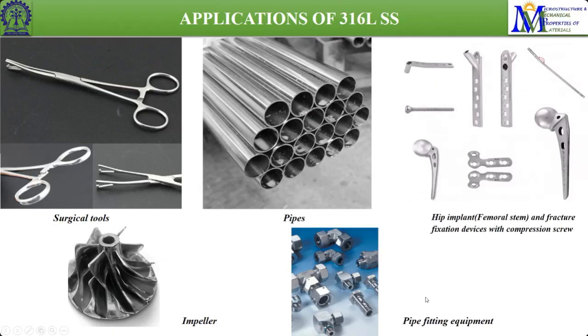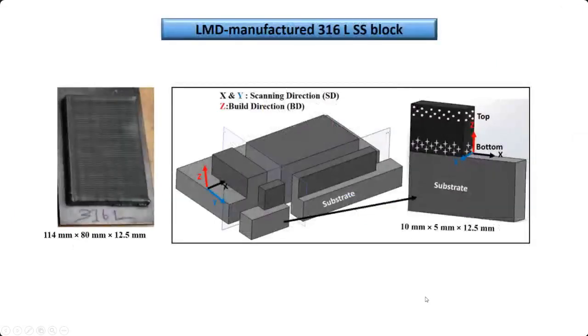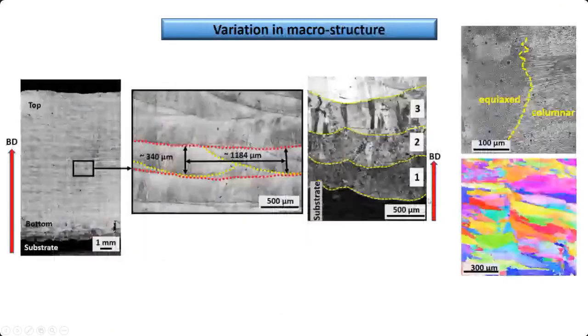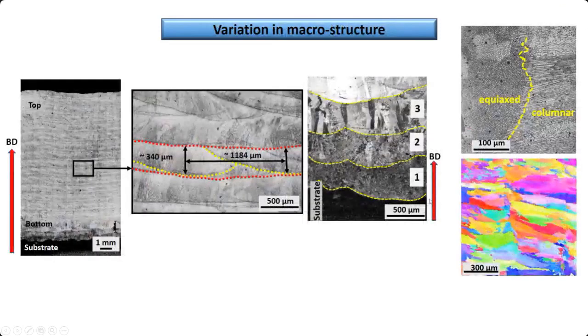Considering the wide applicability of this material, additive manufacturing is also being tried on this material, and we have an LMD manufactured block, laser manufactured block, which we have characterized at different sections and cross sections, parallel and perpendicular to the build direction, and evaluated the microstructures at the top, middle and bottom at different sections.